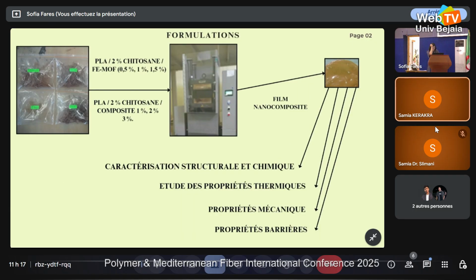Next, please. Then the extruded materials, PLA and all nanocomposites, were cut into uniform granules and dried to remove residual moisture. These granules were then placed in Teflon-lined molds between metal plates and pressed using a hydraulic press at 180 degrees Celsius. Let's now move to results and discussions.